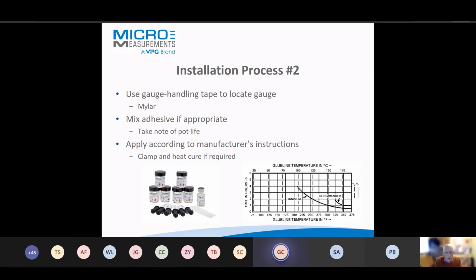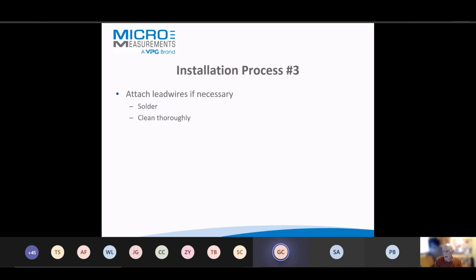And some adhesives will require clamping and heat curing. If you're using an instant adhesive, it might be 1 minute of thumb pressure. If you're using one of the heat cure adhesives, it might be 2 hours in an oven, for example. Once you've completed that cure process, the next stage is to start attaching lead wires. Now, many gauges come with lead wires already attached, but there is no doubt it's better to bond the gauge first, then solder the leads on. You get much better results.